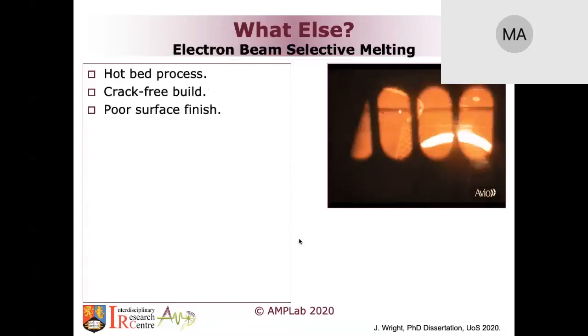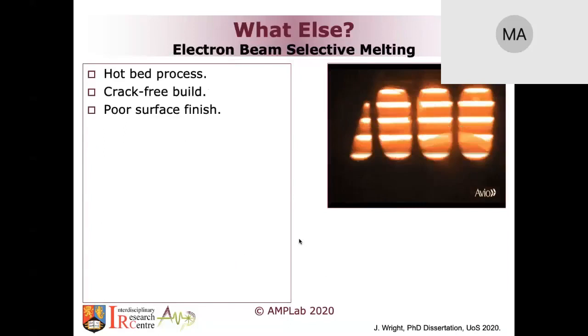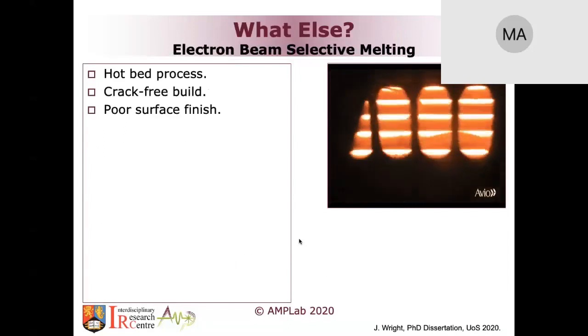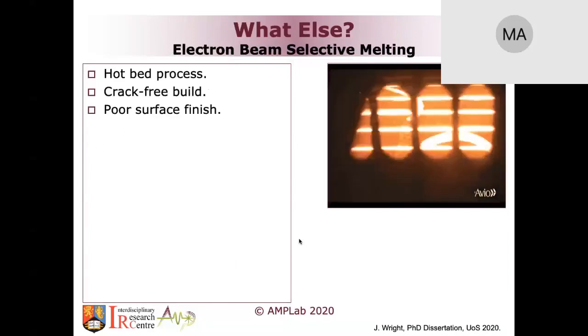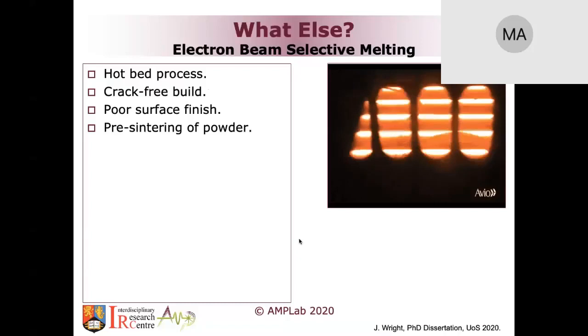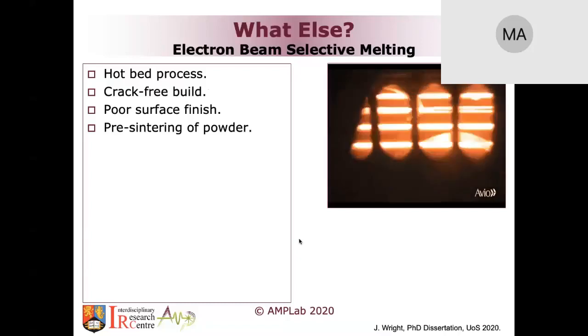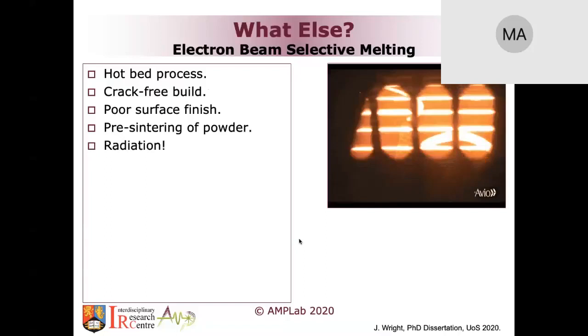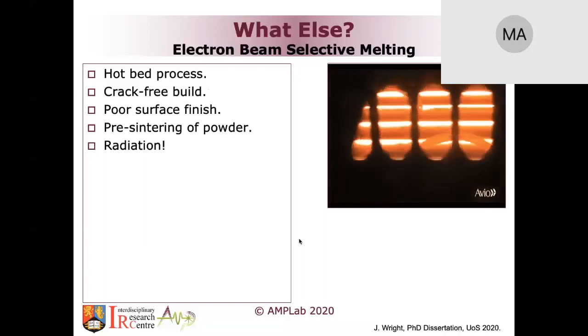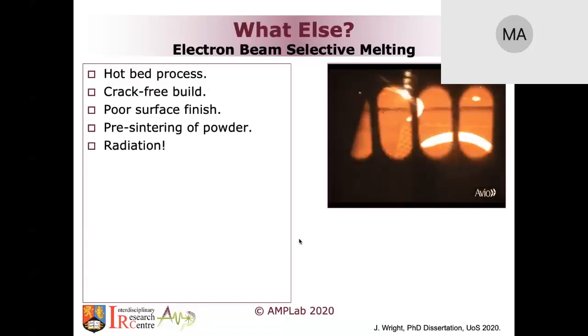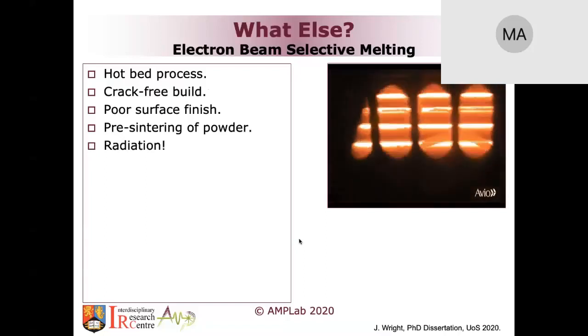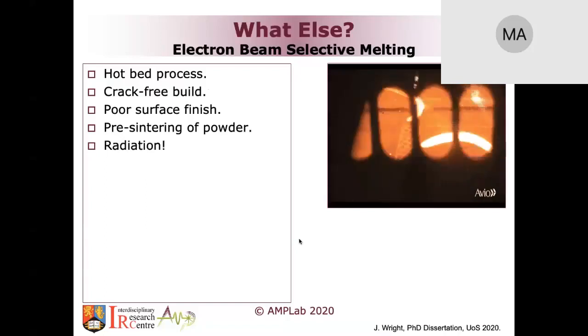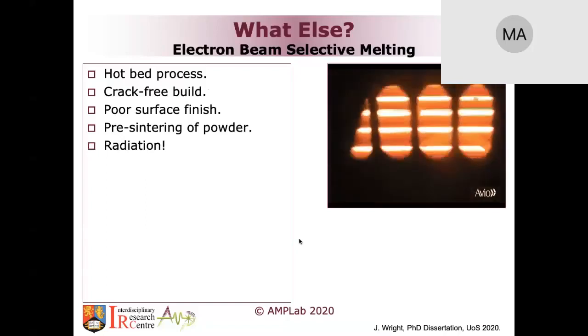The problem here is that because you're using electron beams, not very fine lasers, the surface finish is poor, and you also have to pre-sinter the powder in order for the process to work. More importantly, if you're hitting tungsten with electron beams, you're going to get a lot of radiation. So the machine needs to be radiation safe if you're using electron beam melting.